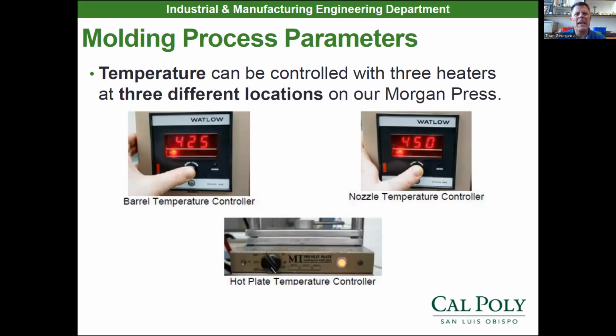Now, we also keep the mold hot. You saw in the video they cool their molds. We don't mold quick enough to need coolant. We have to keep our mold warm because it's made out of aluminum. If we were to inject 500 or 600 degree nylon into a cold mold, it would solidify instantly and not fully fill the mold.